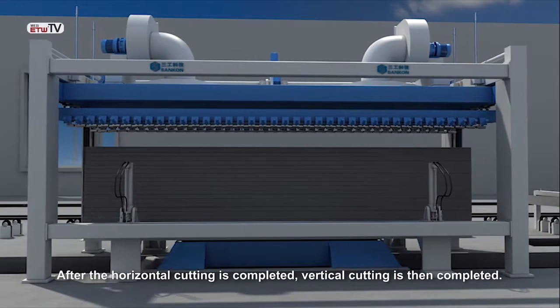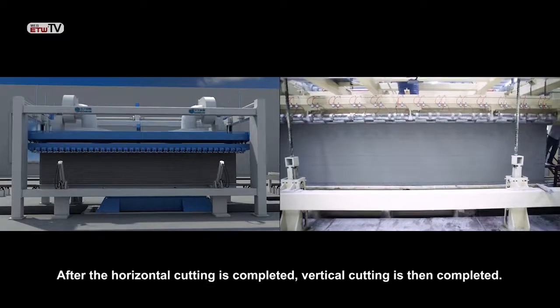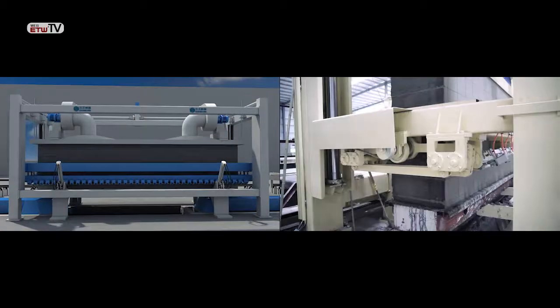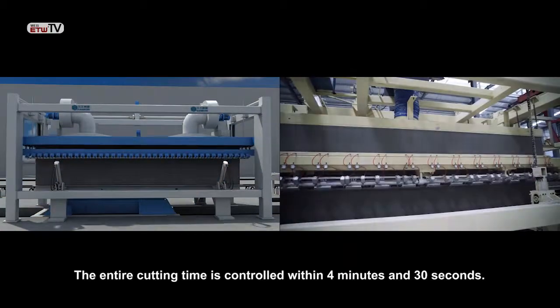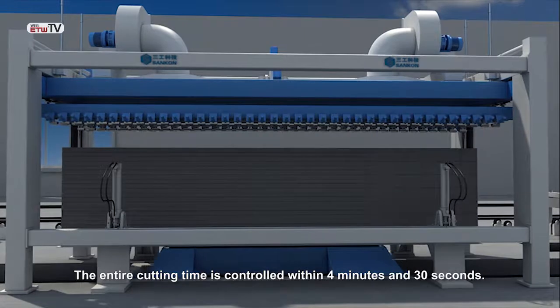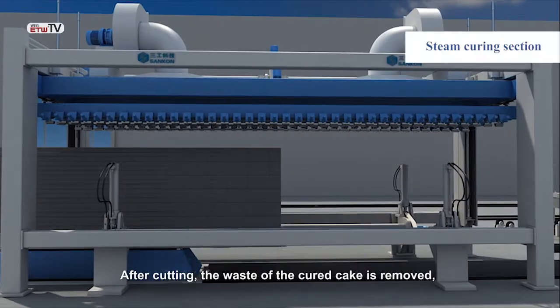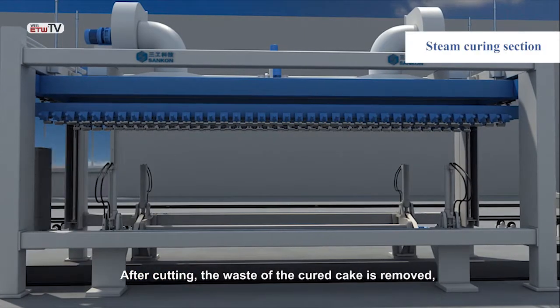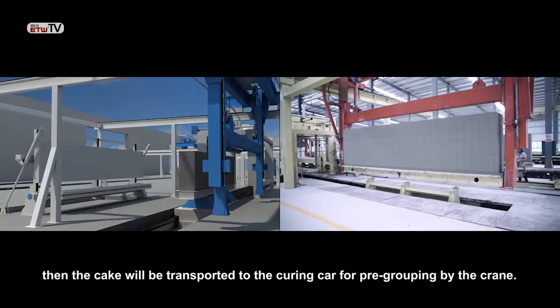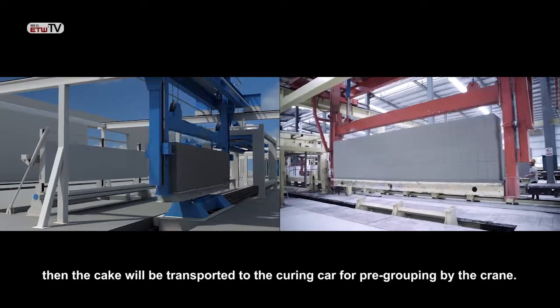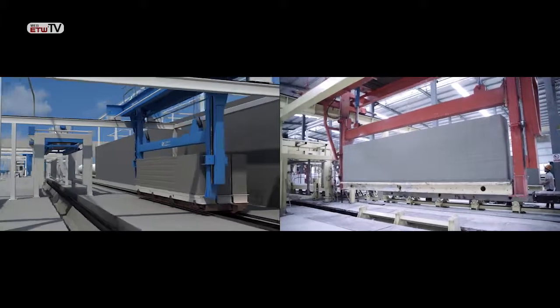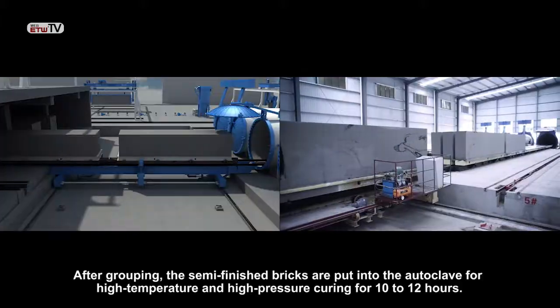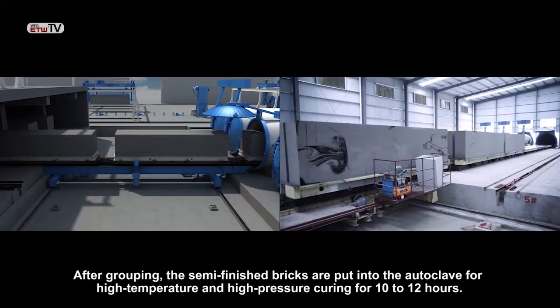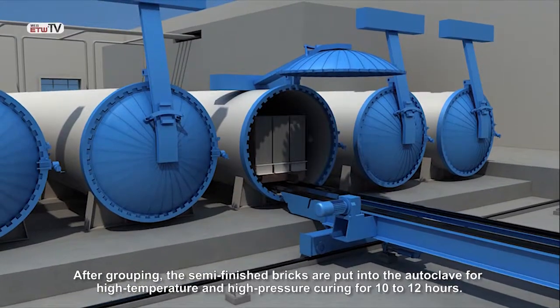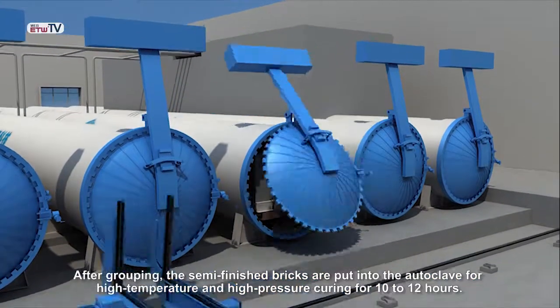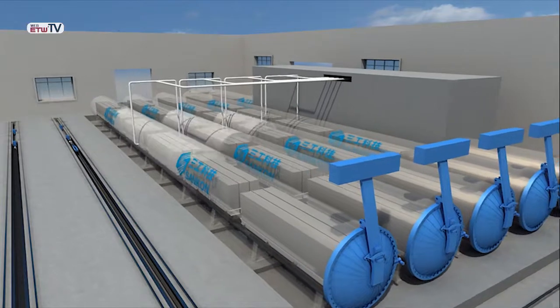After the horizontal cutting is completed, vertical cutting is then completed. The entire cutting time is controlled within 4 minutes and 30 seconds. After cutting, the waste of the cured cake is removed. Then the cake will be transported to the curing car for pre-grouping by the crane. After grouping, the semi-finished bricks are put into the autoclave for high temperature and high pressure curing for 10 to 12 hours.